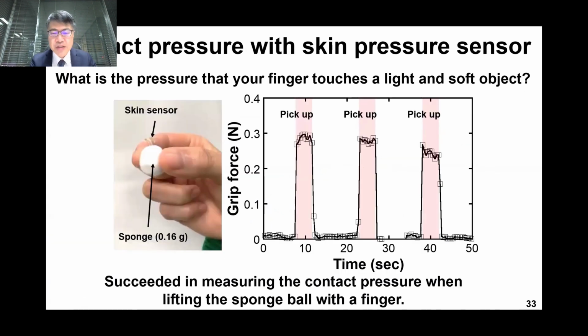And here we monitor the grip pressure while lifting up a very soft sponge with a weight of 0.16 gram, repeatedly picking up and releasing, and succeeded in measuring the contact pressure of such a soft and lightweight sponge ball by fingers.